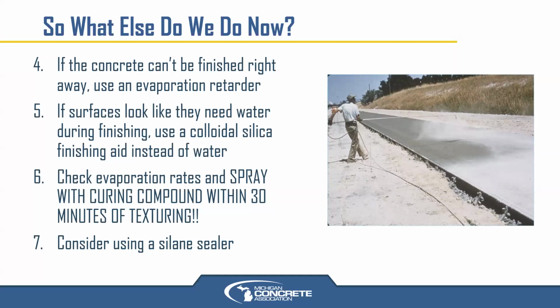But the biggest thing is try to get that curing compound on within 30 minutes of texturing. It's literally pennies per square foot, so it's not expensive. And if you spend that, you're saving yourself the chance of remove and replace, big time headaches, labor and time spent figuring out what went wrong and arguing with an owner. Nobody wants that for their concrete projects.